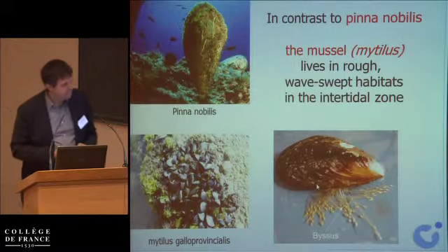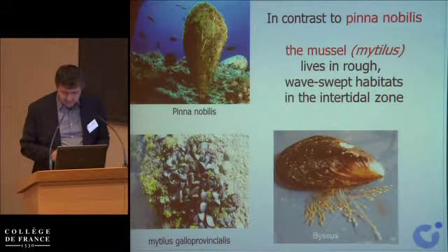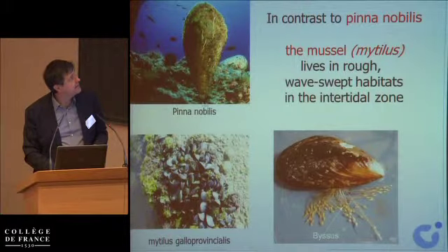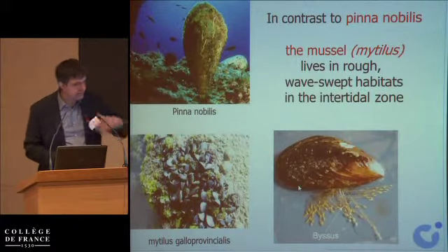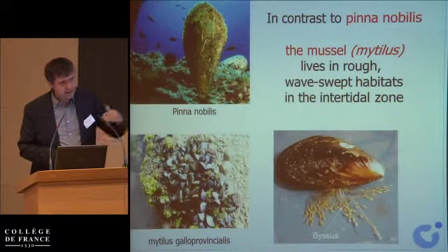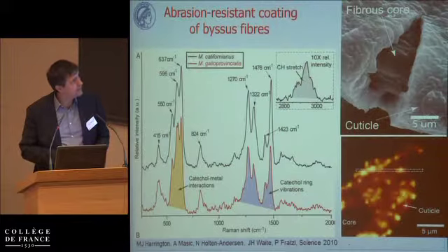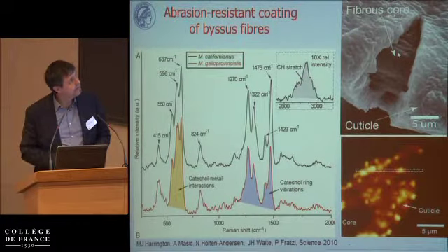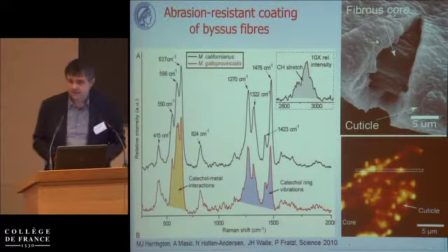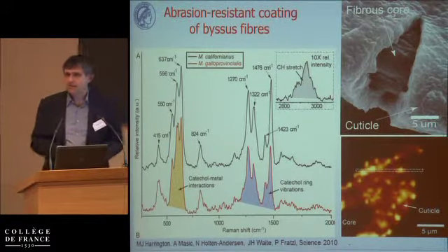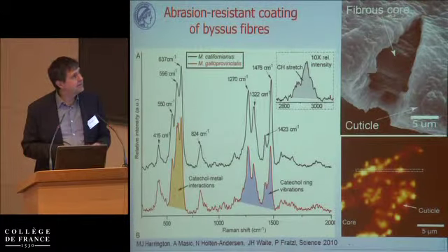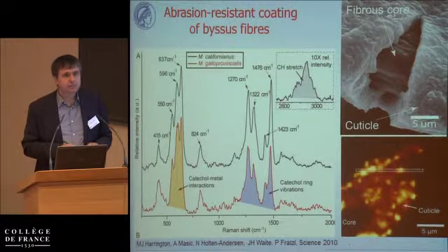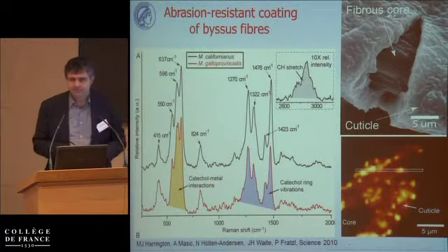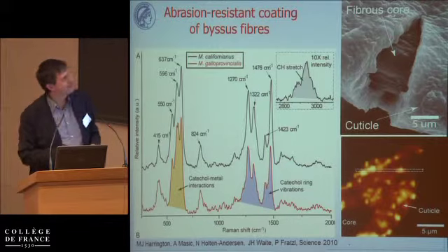Let me go back quickly to the byssus of the mussel, because the pinna nobilis is again anchored by these fibers in the ground, but it lives in fairly quiet sea, while the mussel lives in very, very rough seashores. And so not only does this fiber require interesting properties for the fiber itself, it also requires to be protected against wear. Now, this is the challenge to the engineers in the audience. How do you design a wear-resistant coating for a fiber that has to extend by 100%? This is the challenge that I'm posing to the engineers here.